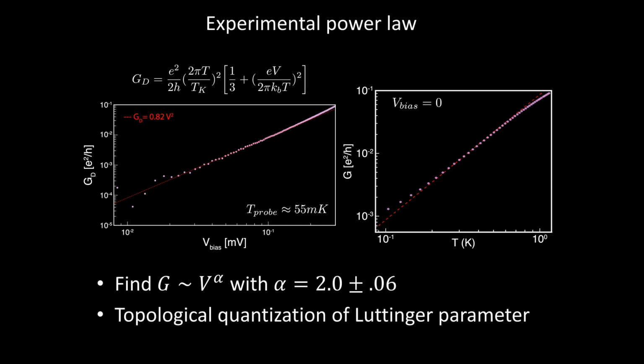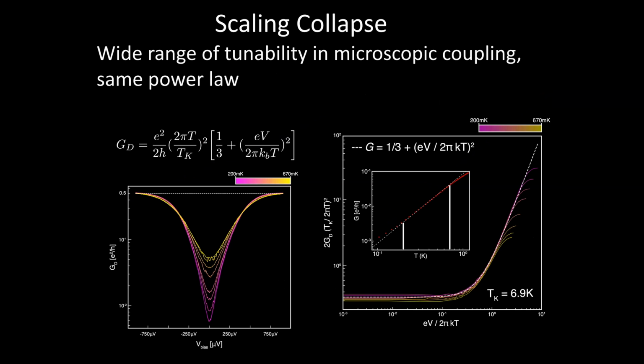You go to some different density, some different filling inside the plateau. You get T squared and V squared, and there's just no tuning, within a couple of percent. So things work very nicely. We see this universal regime. But it turns out to be an even more interesting problem than that, because you can now try to study this over a very wide range of parameters. In particular, you can ask, does everything work quantitatively? If I make the barrier bigger, then this regime should go to lower temperatures. Can you do that? Yes, it all collapses to this beautiful scaling curve, right?